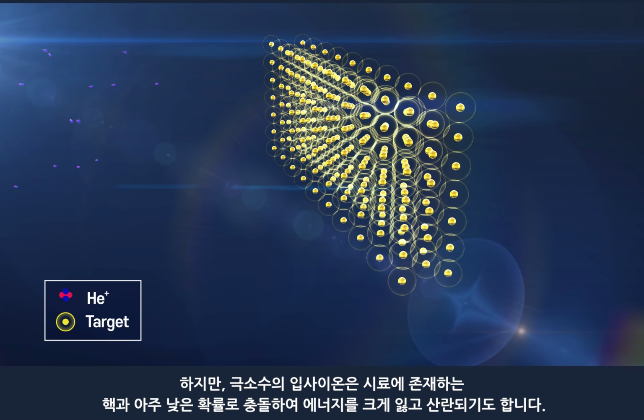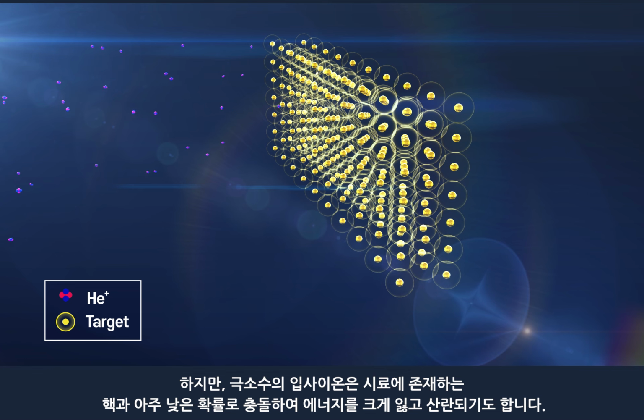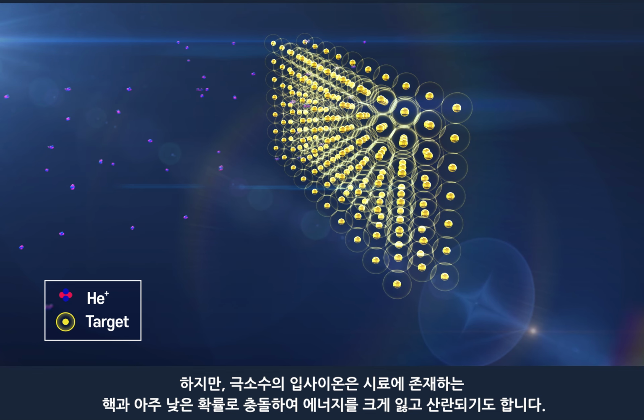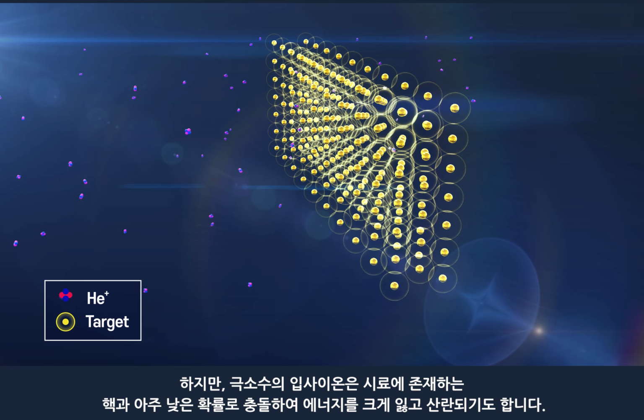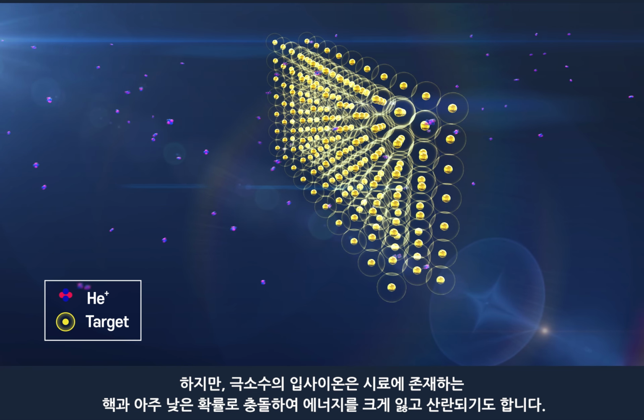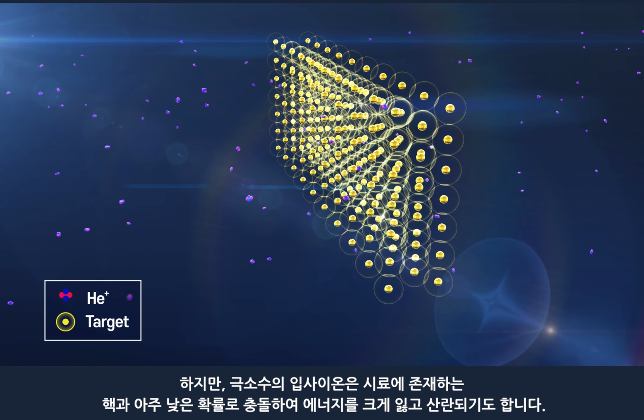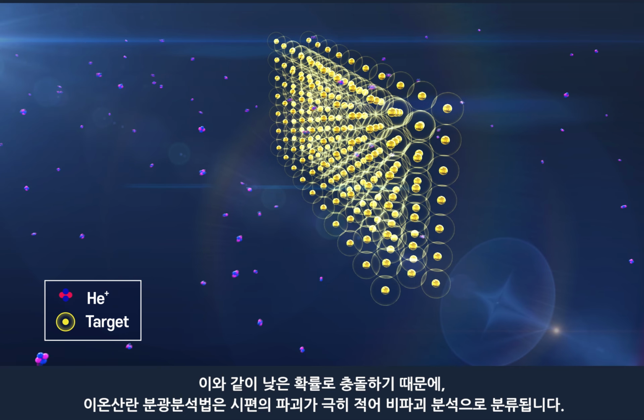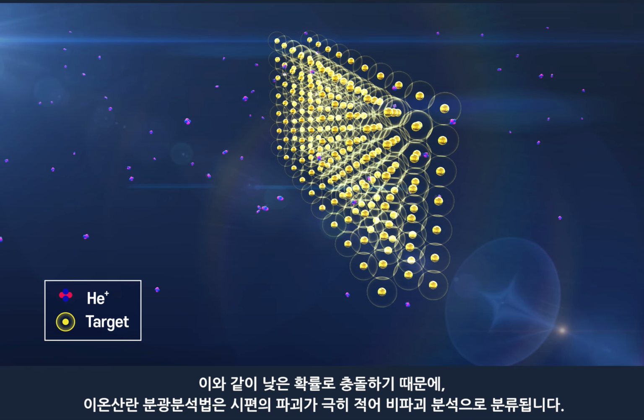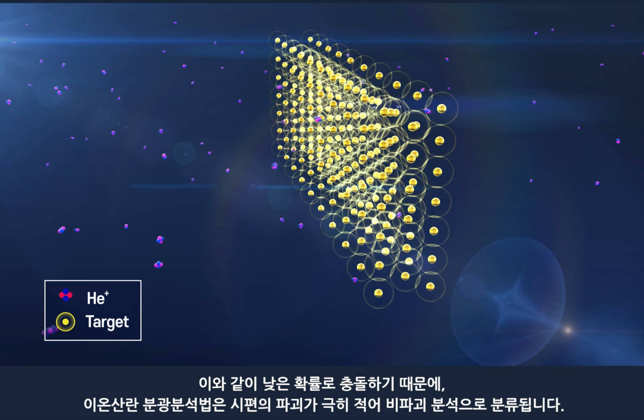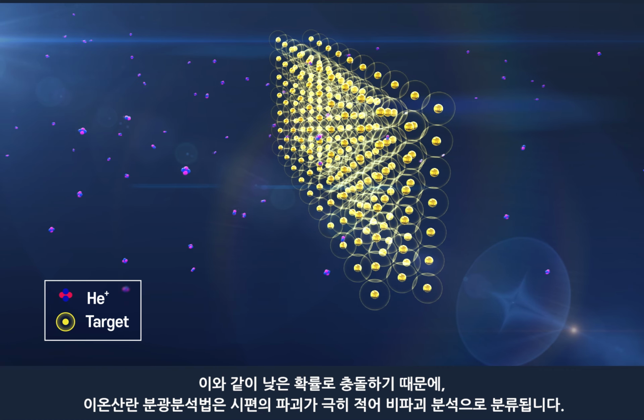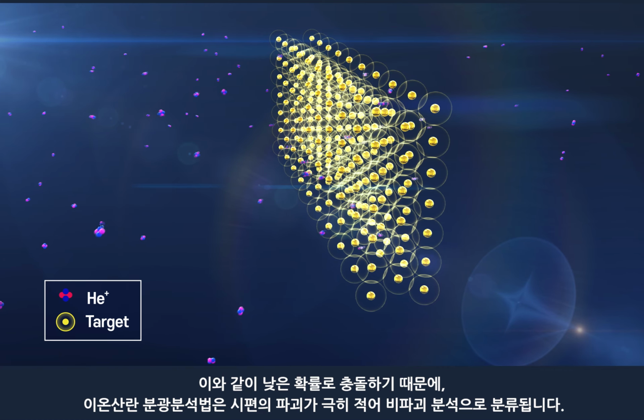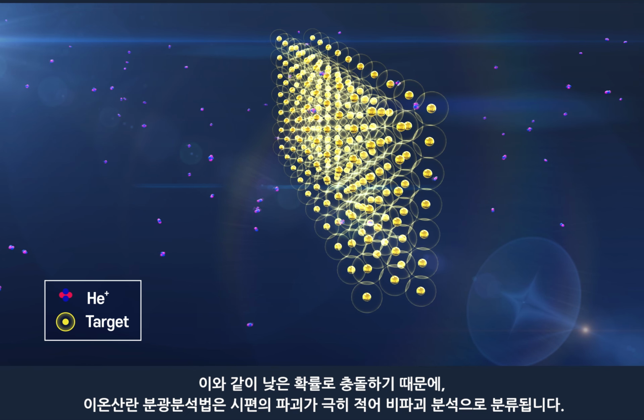However, a considerably small number of incident ions collide with the nuclei present in the sample with a very low probability, resulting in scattering and significant energy loss. In addition, because of the very low probability of collision, the sample destruction is very small. Therefore, this can be classified as a non-destructive analysis method.